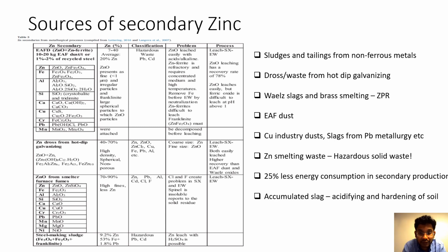This was an article from Hydrometallurgy. They talk from the perspective of hydrometallurgy. So you could see that one of the problems they say is that you have to remove iron prior to electrowinning. So that's one problem. And then there is also sometimes the formation of what's called franklinite, ZnFe2O4. That's something that's tough to leach. And when you have formation or existence of that in your residue, it's not so easy to leach, simply because of the complexity of the crystal structure.